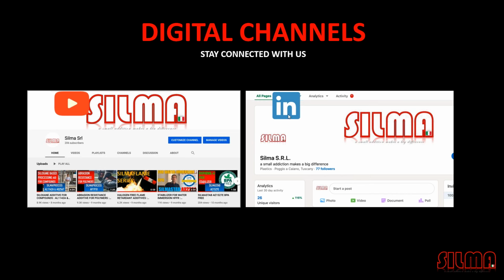That's why it is important to control the properties of our thermoplastic partner for the silicone additive. Also, we developed the interpenetrating network technology, IPN, to create new thermoplastic siloxane hybrid materials. You cannot distinguish anymore where is the silicone additive and where is the thermoplastic. It can be PET, polyamide, or PP, because the 3D IPN structure, in practice, creates a new block polymer.